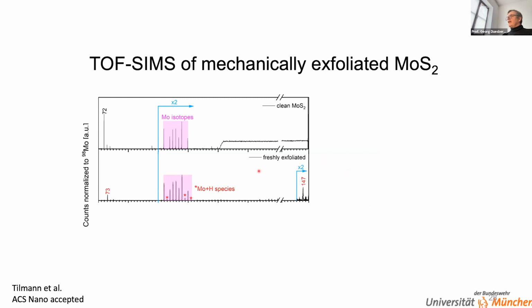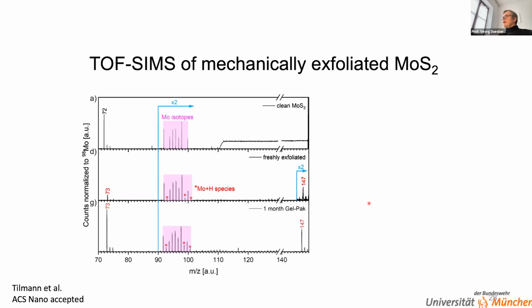This is a freshly exfoliated flake. So this is not CVD grown. This is exfoliated, but not in touch with the polymer. That's just from the standard mechanical exfoliation procedure. They use polymers in the vicinity to swipe it, but not on the surface. And then you can see already this molybdenum plus hydrogen species showing up here, and those peaks associated with PDMS.